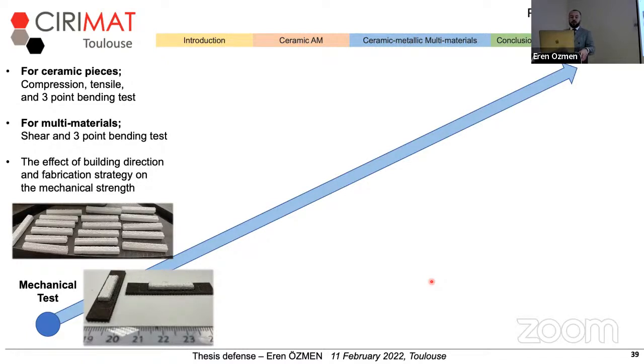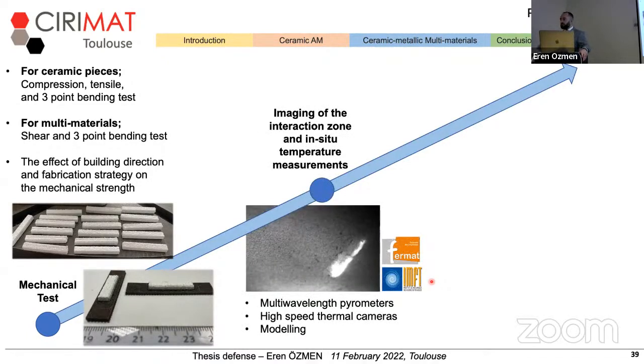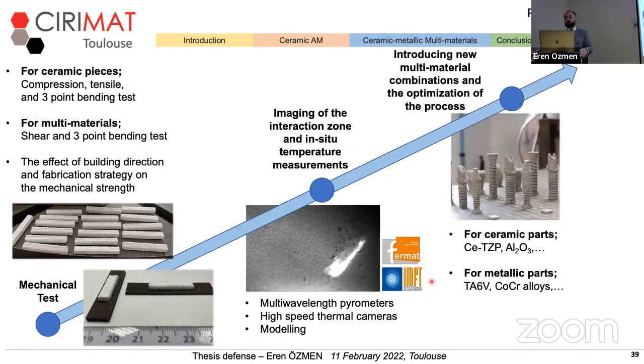test. And as a second step of perspectives, I would offer imaging of the interaction zone and also measuring the actual temperature of the interaction zone to understand much better which temperature we are reaching, what the possible kinetics at this temperature are, and that will be very helpful to understand the creation of phases in the structure. And this can be done by using multi-wavelength pyrometers or high-speed cameras, or with a combination of modeling, for example.